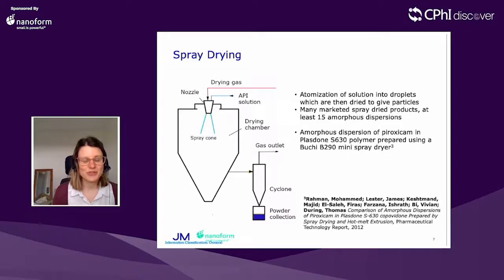that's passed through a nozzle, and this atomizes that solution into droplets. Those droplets then travel down a drying chamber where they're exposed to drying gas, which evaporates the solvent, giving particles which are then separated from the drying gas, generally through a cyclone. So spray drying is commonly used in the pharmaceutical industry, both for amorphous dispersions and then also for other